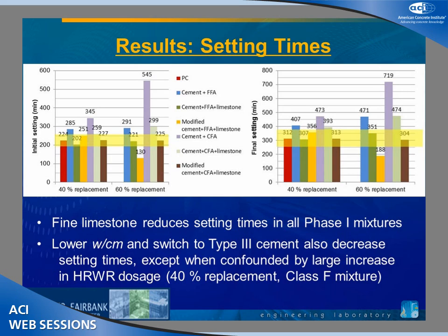What you can see is that in general, if we just take an example here, as we add F-ash into the system, our initial set went up to 285 minutes. With the C-ash, it went up to 345 minutes. But in both those cases, when we added the limestone powder in, we easily got our setting time back into the range that we were looking for.